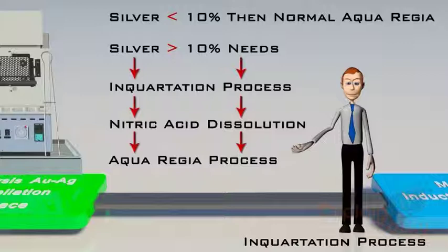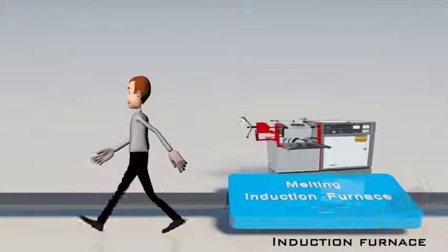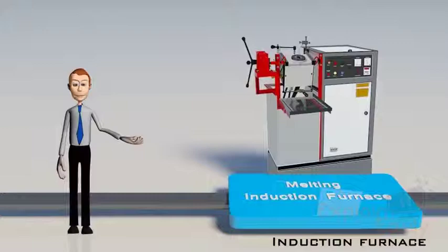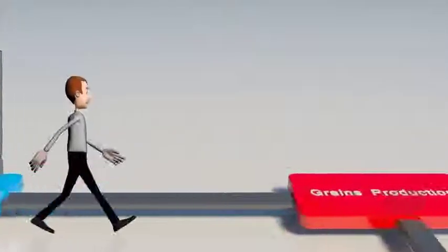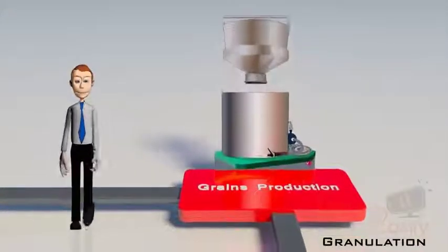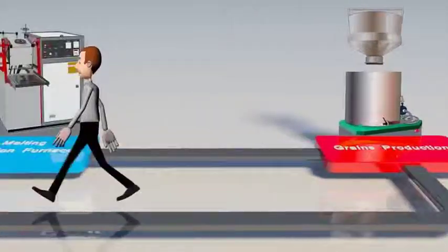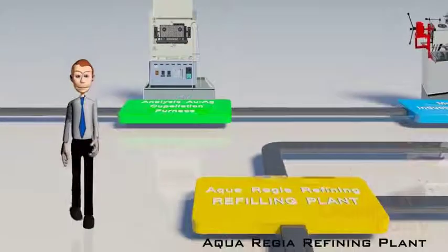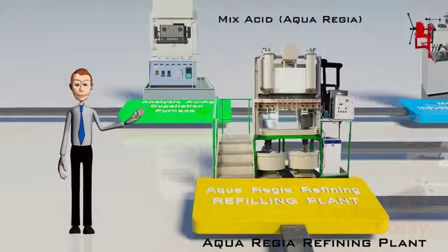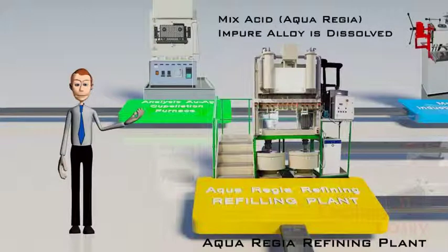After assaying, the raw material, which is impure gold, is melted in an induction furnace. After melting, it is granulated in the granulating unit, which is in the form of grains or flakes, to be fed to the aqua regia reactor. The aqua regia refining plant comprises of steps: mix acid, that is, aqua regia reaction as the first step, where an impure alloy is dissolved. Steam or heating is used as a step to enhance reaction and ensure good efficiency.